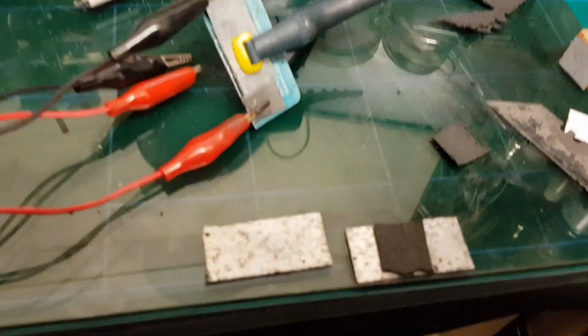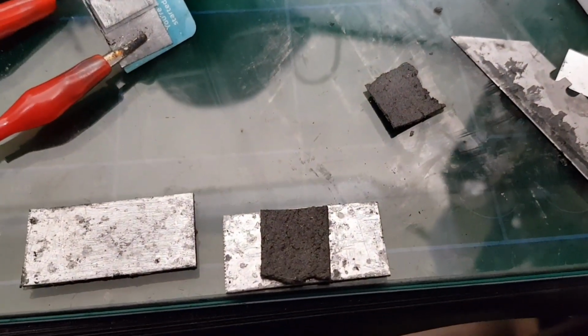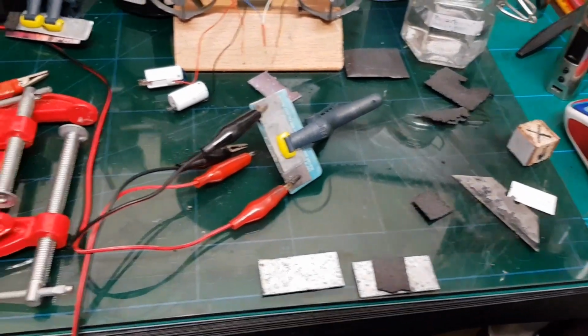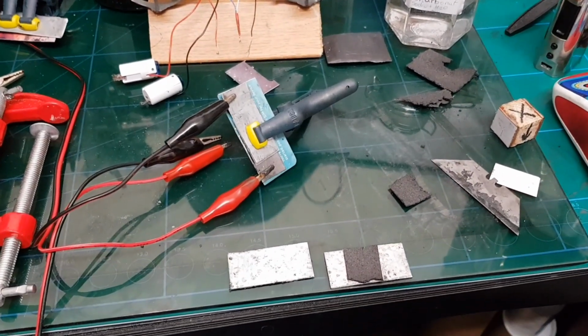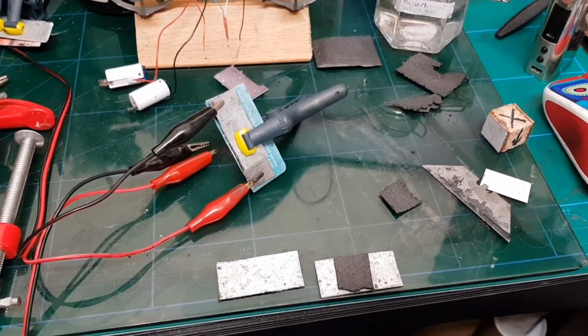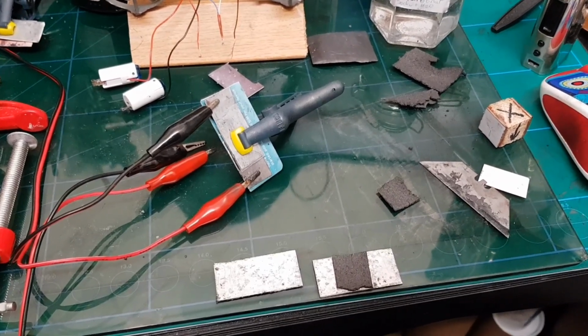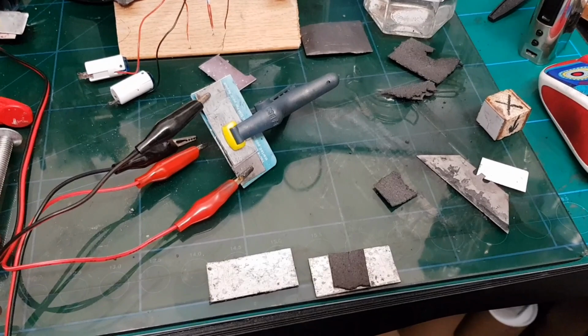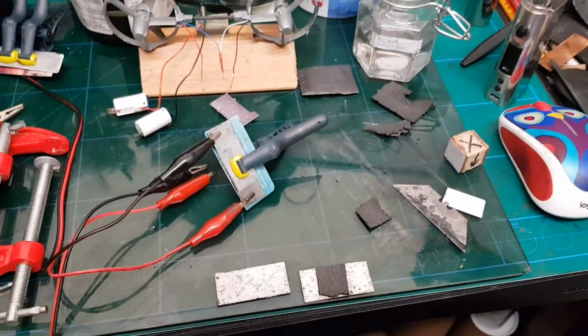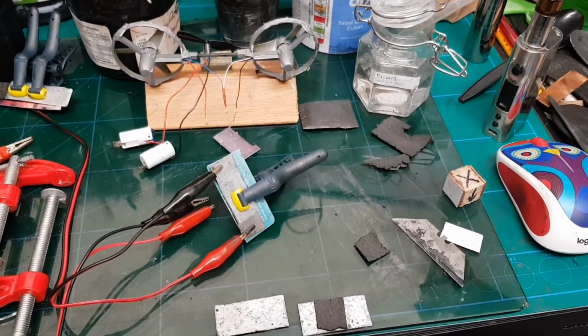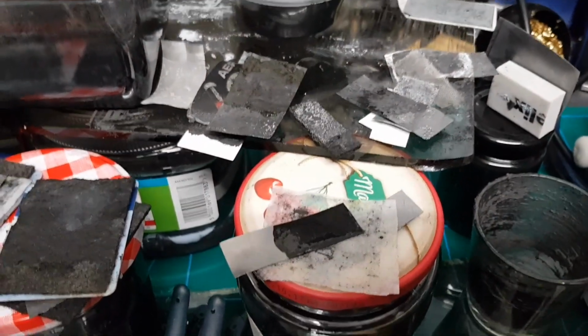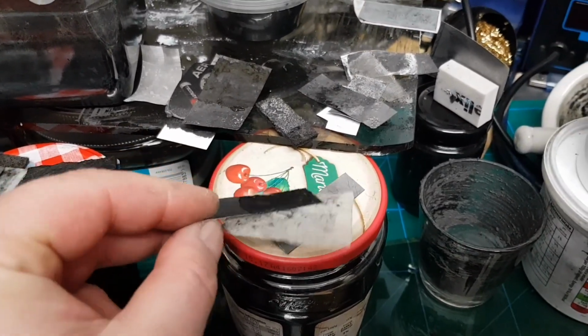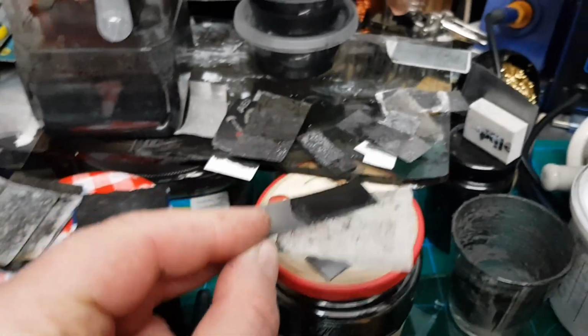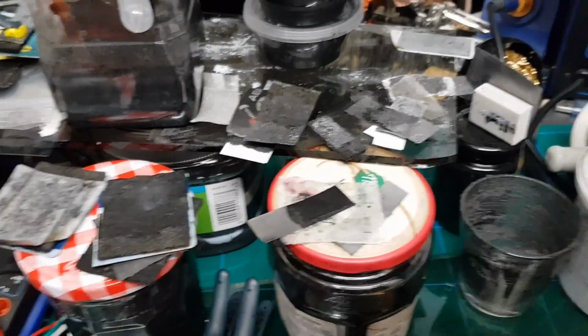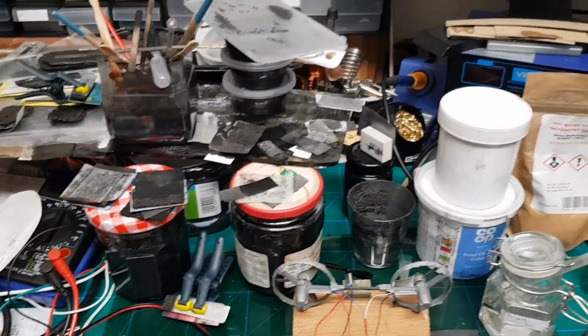What I'm going to do is cut it into two more pieces. And what I'm going to try is to put them in between two aluminium plates and then press them with two adjustable clamps, and see if that is going to change the performance of the material drop casted straight on the glass. Yeah, I'll carry on charging and discharging the other one, but at the same time I'll carry on with pressing this one and adding a few layers to this graphite foil, to see how this is going to change the performance. Yeah, I'll come back a little bit later.